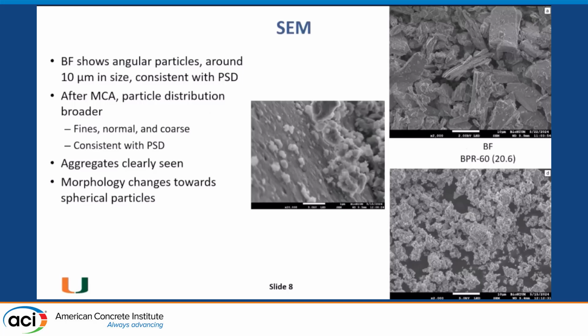So we put these under the electron microscope. Unsurprisingly, the results are rather consistent with the particle size distribution. The raw basaltic fines, the particles are quite angular in nature. They're about 10 microns in size. After MCA, the particle size distribution is clearly broader. And we do see fines, about 10 micron particles, and coarser particles. So that's very consistent with the PSD. And we see some sort of aggregate or agglomerative behavior. The other thing we see is, generally speaking, we haven't quantified this yet, but there seems to be a marked change in the morphology.